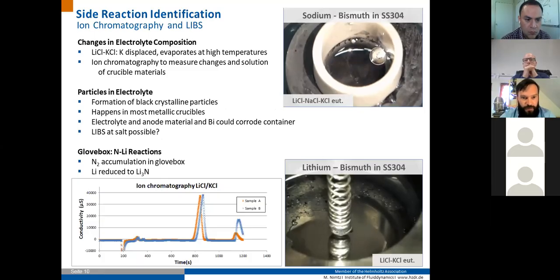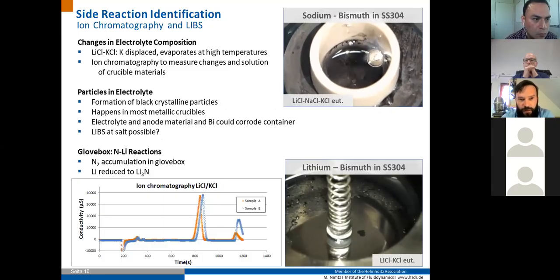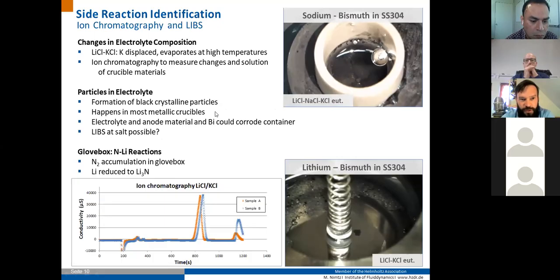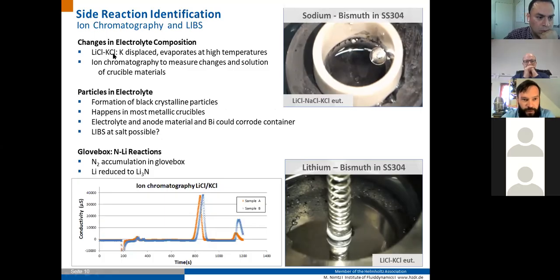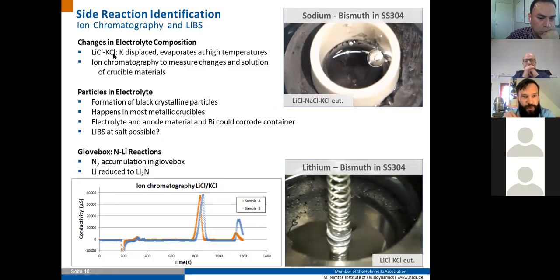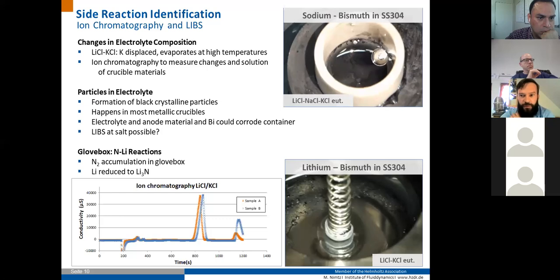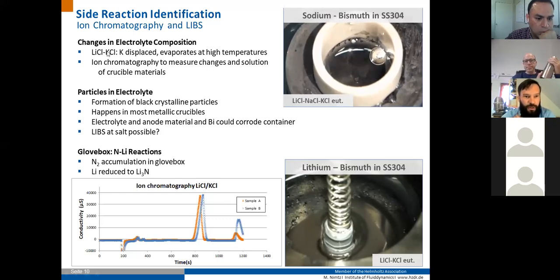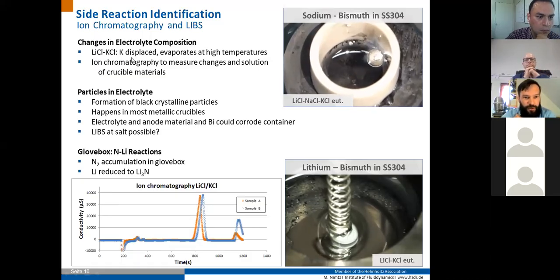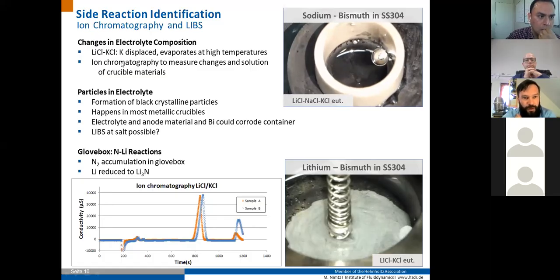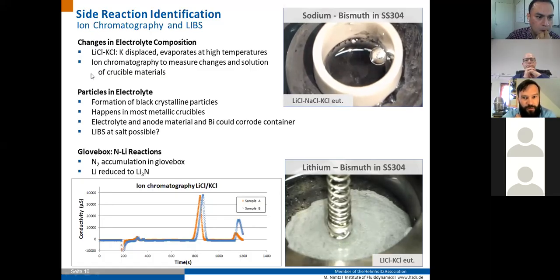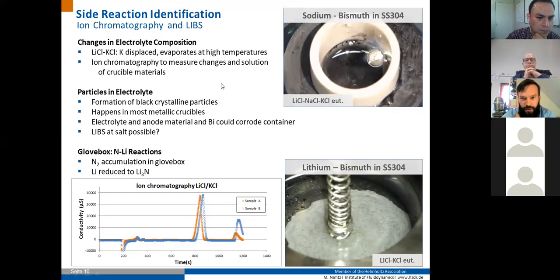To identify side reactions in the electrolyte, especially changes in electrolyte composition, as I said, for example, if you use lithium chloride, potassium chloride as an electrolyte, which is quite common to use, or would be the first choice to use because it's readily available and used in industry as well, here we observed displacement of potassium in the electrolyte, which led to the change of the electrolyte composition.